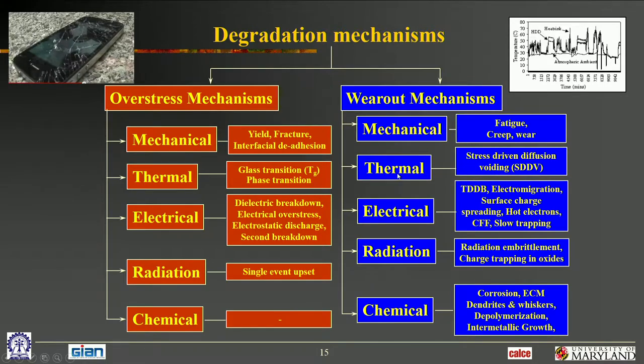We do a thermal analysis using methods that Professor Anandaroop talked about, and that gives me the temperature at the failure site. Then I input that temperature, not the ambient temperature, the local temperature that we get out of the calculation at the failure site, into the model, pull out the material constants, and I can predict how long it takes for cavities to grow in, let's say, aluminum metallization, as an example. So stresses are needed, material properties are needed, quantitative models are needed, and they're all available.